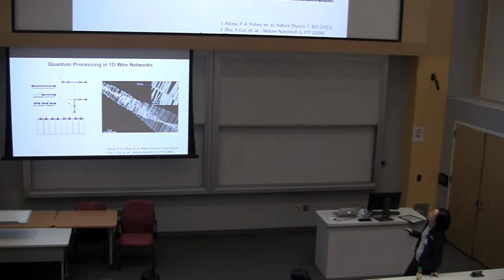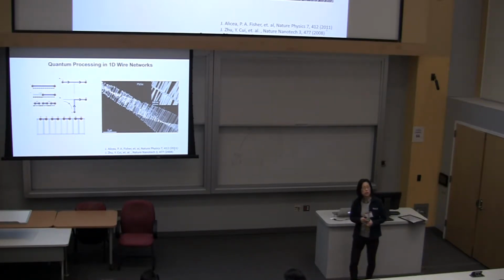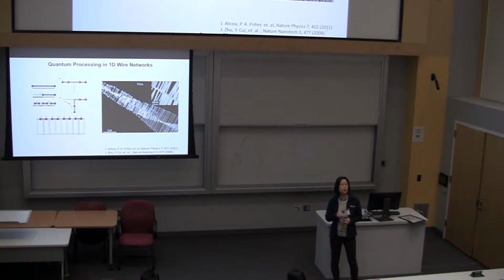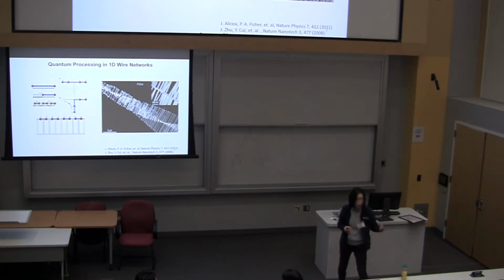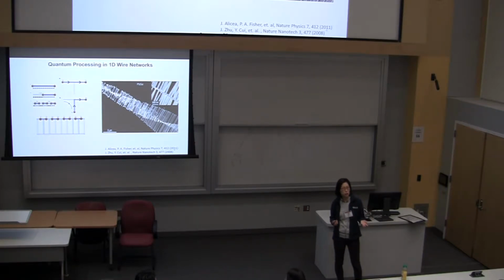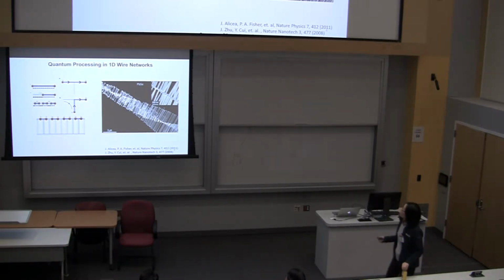Okay, so you can imagine having networks of these topological superconductors, and making qubits out of topological superconductors is beneficial compared to other existing qubits because there's no phase decoherence problem. Okay, so in existing qubits, the phase goes out of coherence due to noise fluctuations, either thermal or electrical noise fluctuations. Here, theoretically, we're not supposed to have that problem, okay?